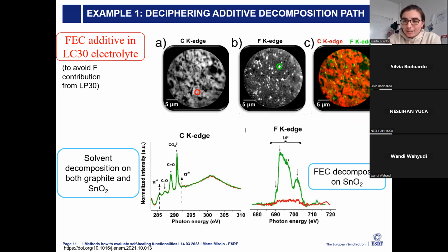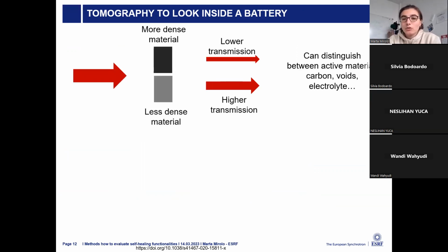However, when we look at the fluorine K edge and we look at the different active materials, then we clearly see that the FEC is decomposing only on the tin oxide. And the fact that the FEC is decomposing only on the tin oxide is probably creating a bit thicker SEI, which is probably a bit more flexible, which leads to the improved electrochemical performance of the graphite tin oxide electrode when the FEC additive is used. So the next example that I will bring is based on tomography. Tomography is a technique which is used to really look inside the batteries, inside the materials. It's really like using a magnifying lens to look inside the battery without having to open it.